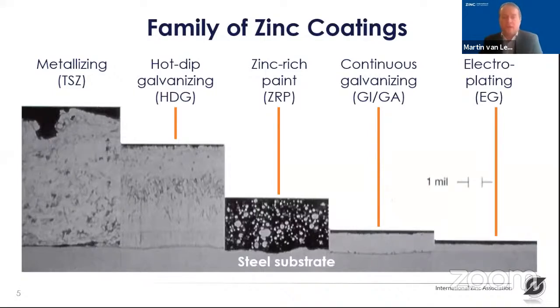The third category are zinc-rich paints. Here, a paint with a high level of zinc pigments or metallic zinc dust is applied on a steel substrate. And also here you are flexible in thicknesses, but typically these paints are applied with a thickness of 60 to 80 micrometers, but we will hear much more about zinc-rich paints in a later presentation today.